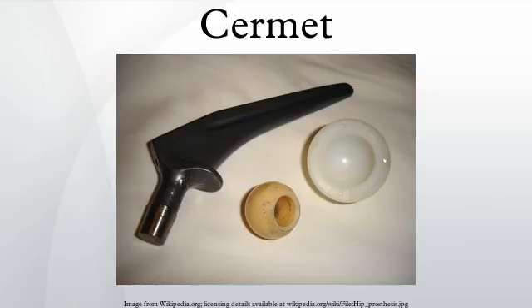Ohio State University was the first to develop Al2O3-based cermets with high-stress rupture strengths around 1200C. Kennametal, a metalworking and tool company based in Latrobe, Pennsylvania, developed the first titanium carbide cermet with a 2800 psi and 100-hour stress-to-rupture strength at 980C. Jet engines operate at this temperature and further research was invested on using these materials for components.